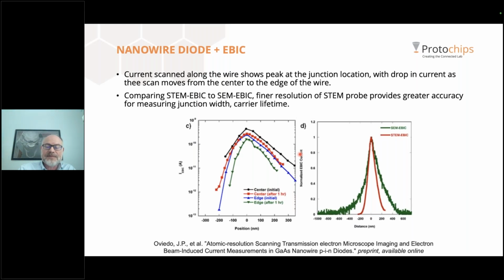On the right, you can see SEM versus STEM data. Here, because of the finer probe size of the STEM, though there's less current overall, you get a finer resolution that allows you to better localize the junction and make accurate measurements of carrier lifetime.